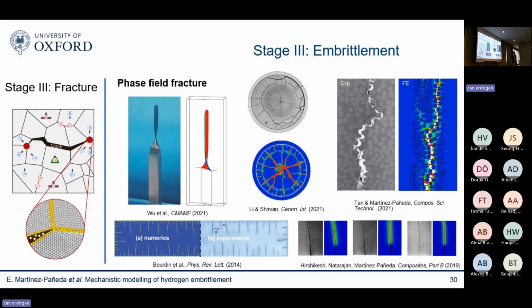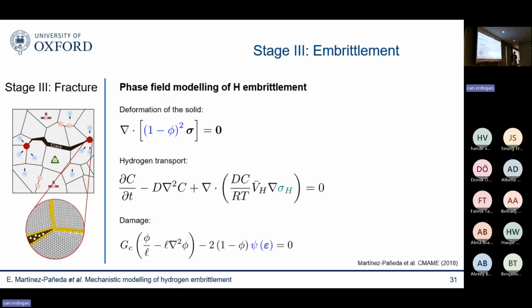And this slide overviews a little bit of why phase field has become so popular in the fracture mechanics community. You can see here, for a wide range of materials, metals, ceramics, composites, functionally graded materials, not only is the method able to capture very complicated cracking patterns, but it is able to do so showing a remarkable agreement with experiments. So this is the takeaway. The method, in my opinion, is physically sound and is computationally very robust. So I think we're well equipped.